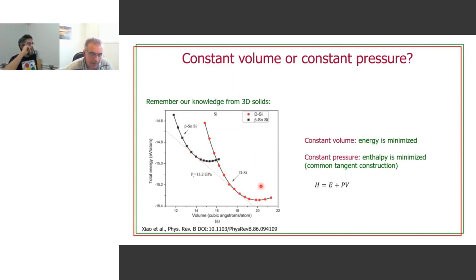The way to do these calculations is to draw what we call the common tangent. This is the common tangent procedure. The slope of this line is the energy divided by volume, so the slope of this line gives you a pressure, and that's the pressure that will lead the system from the diamond structure to the beta-tin structure. So at a certain pressure, there is a discontinuity in volume. The system jumps from here to there, right? And this is how phase transitions in solids take place. This procedure is equivalent to minimizing the enthalpy. We can easily show that this common tangent construction is equivalent to seeing which structure has not the lowest energy, but the lowest enthalpy, okay?